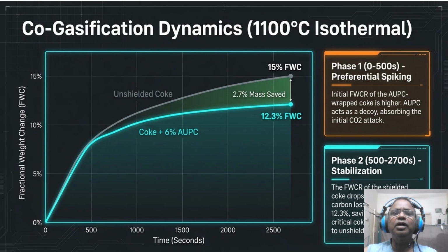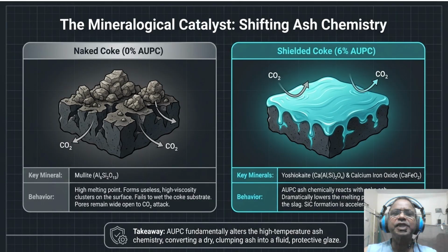So now coming to the mineralogical catalyst agenda, that is shifting ash chemistry. Now this is where the mineralogy takes over. We are moving from dry clumping to fluid sealing. On the left, naked coke forms mullite, with its high melting point and high viscosity, and look, it's useless. On the right, our shielded coke is forming calcium iron oxide. We are seeing a fundamental shift in high temperature ash chemistry.